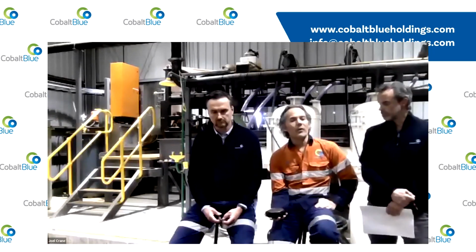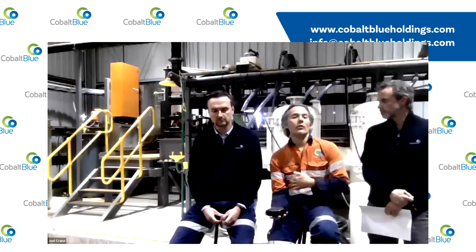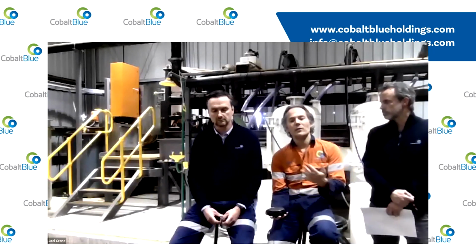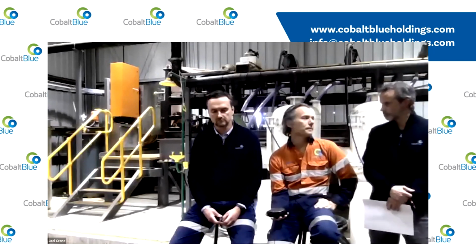The practical outcome of that is that in our concentrator circuit, we're seeing more pyrite go to the gravity because it's coarser than to the float, which would be finer. Whereas when we did the pilot plant work, we found that the quantity of pyrite in the float was larger than what we're seeing now.